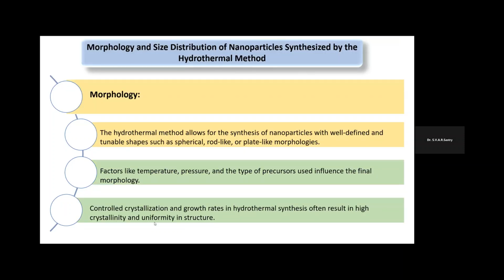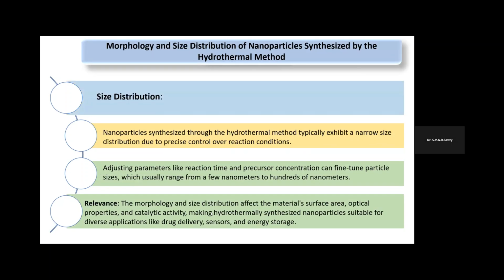Then morphology and size distribution of the nanoparticles synthesized by the hydrothermal synthesis method. This method allows for the synthesis of nanoparticles with well-defined, tunable shapes like spherical, rod-like, or plate-like morphologies. Factors like temperature, pressure, and the type of precursors used can influence the final morphology of the product. Controlled crystallization growth rates in hydrothermal synthesis often result in high crystallinity and uniformity in the structure.